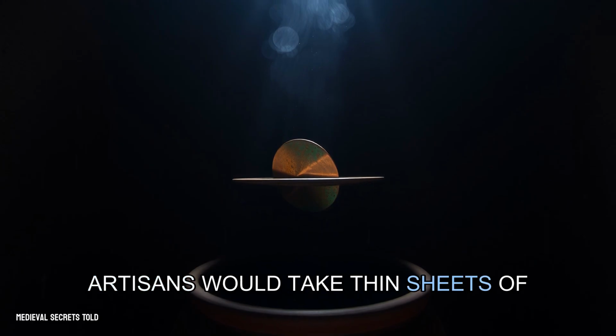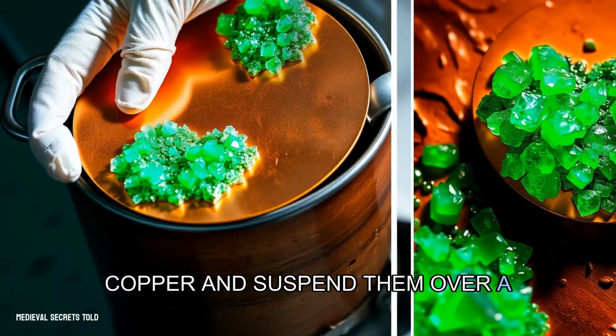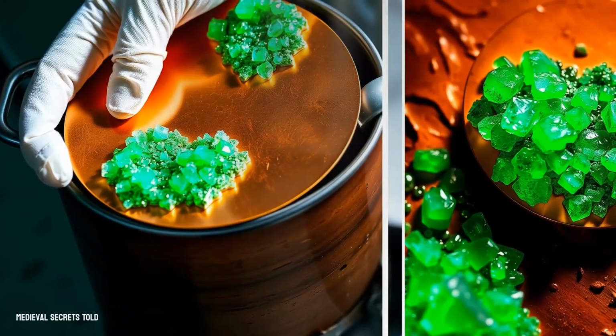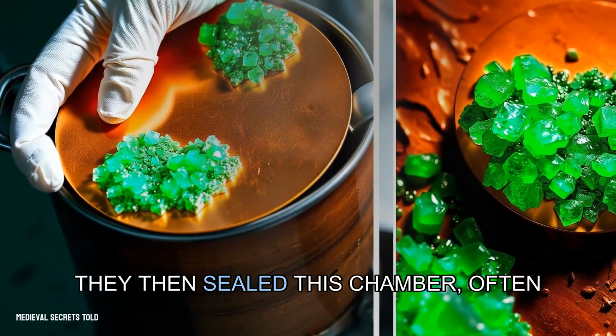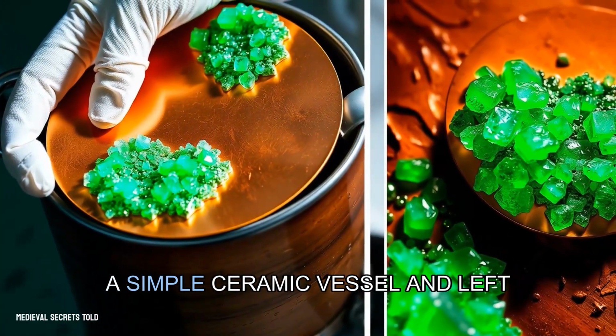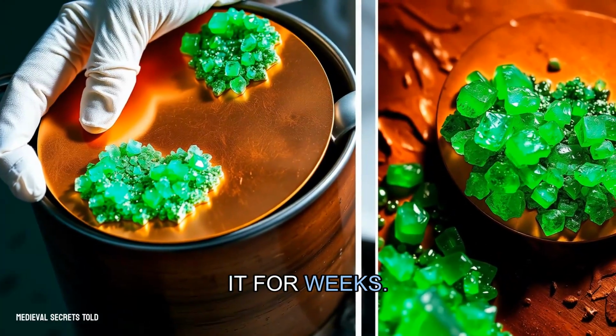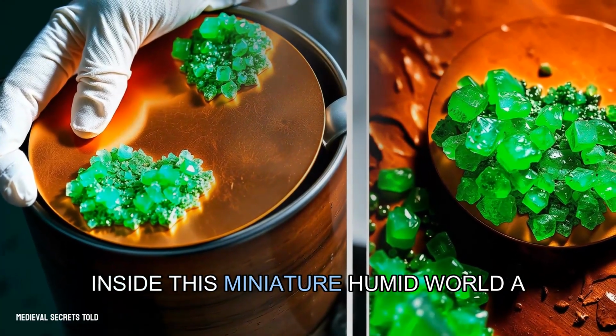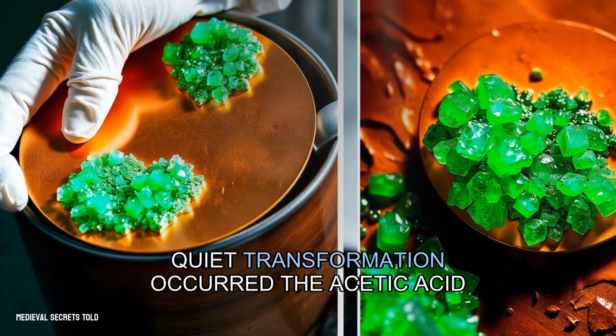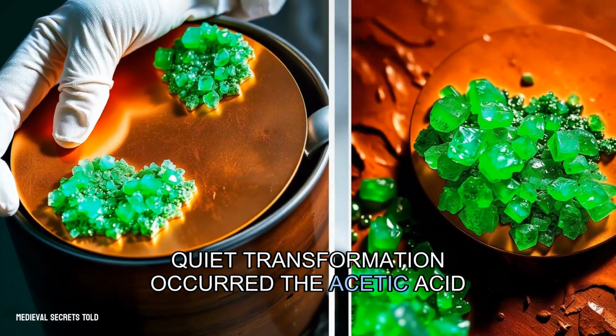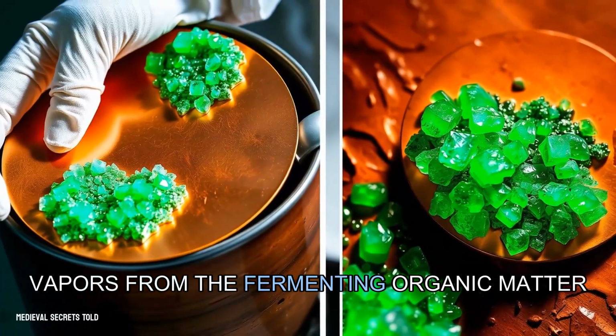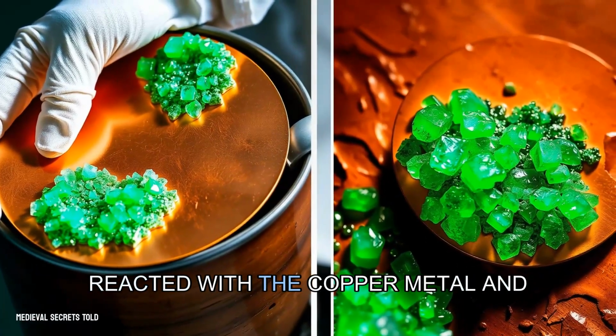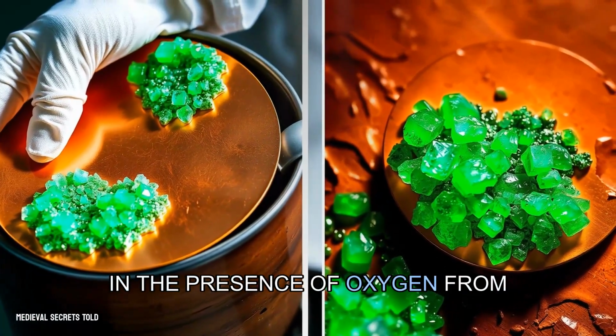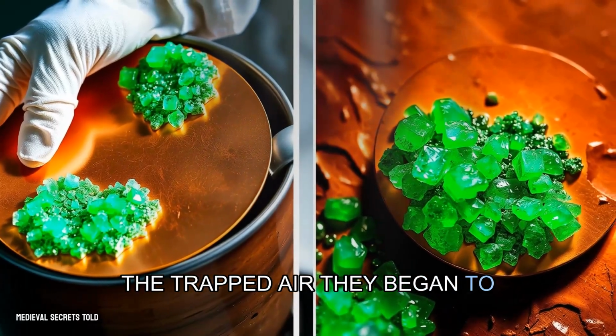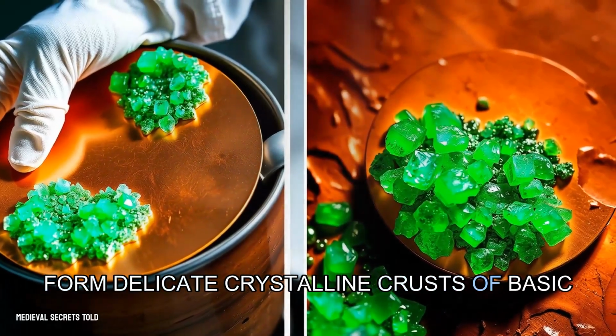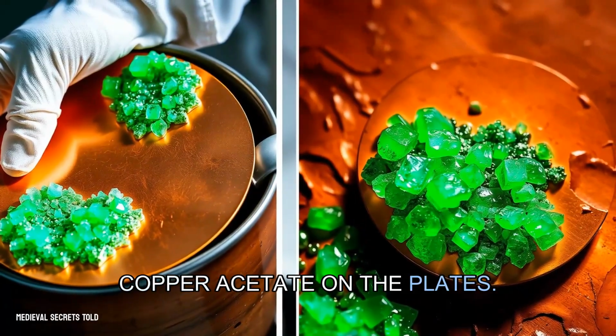Artisans would take thin sheets of copper and suspend them over a pot of fermenting grape skins or strong vinegar. They then sealed this chamber, often a simple ceramic vessel, and left it for weeks. Inside this miniature, humid world, a quiet transformation occurred. The acetic acid vapors from the fermenting organic matter reacted with the copper metal, and in the presence of oxygen from the trapped air, they began to form delicate, crystalline crusts of basic copper acetate on the plates.